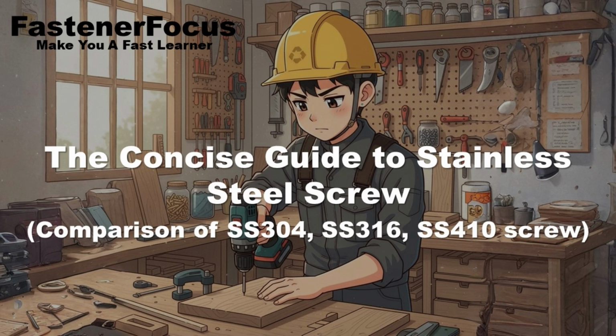It is. If the site is C3 or lower, passivated 304 is usually the most cost-effective solution, balancing excellent resistance with manageable material costs. If the site is C4 or C5, meaning heavy industrial pollution, high humidity, or coastal exposure, then 316 is no longer a luxury. It becomes a mandate to meet the design life. Underspecifying is a technical and financial guarantee of early failure. Conversely, using 316 in a C1 environment where 304 would last 100 years is financially wasteful, albeit technically safe.